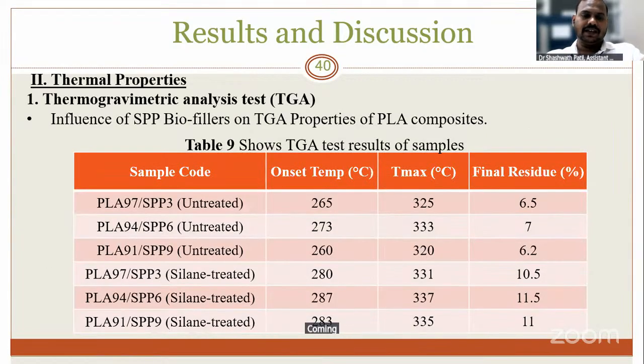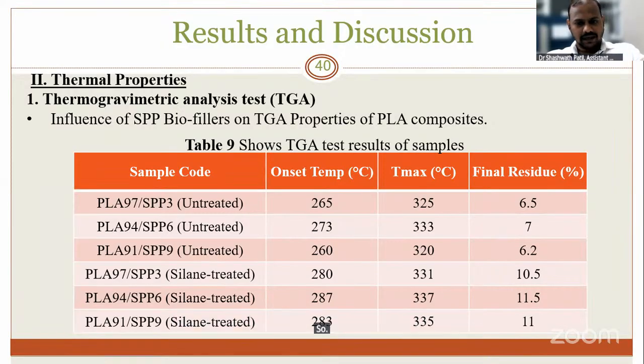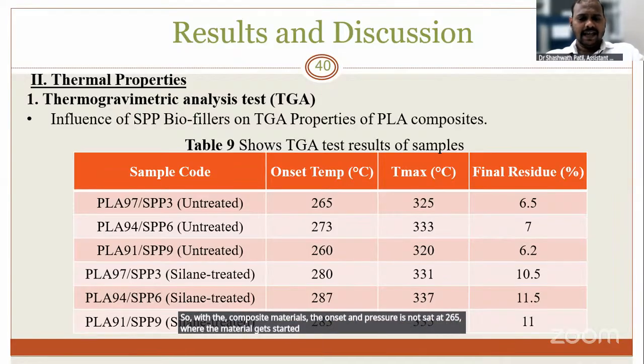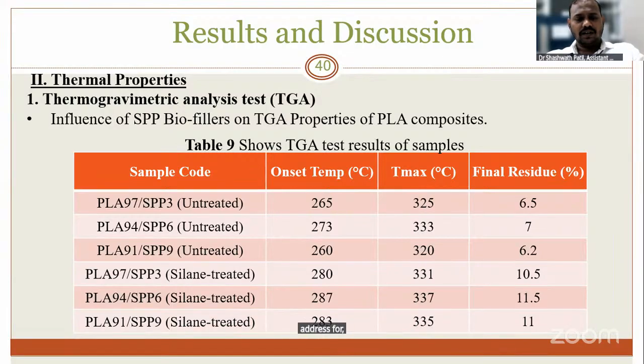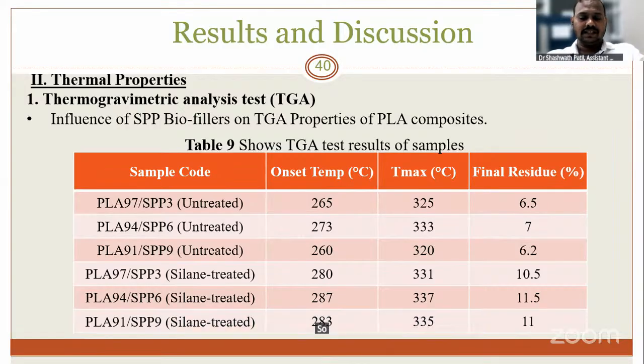Coming to the thermal properties, the influence of the reinforcement material on the PLA: usually PLA has a melting temperature in the range of 150 to 160. With the composite material, the onset temperature started at 265, where the material starts degrading, and it reached up to 283 degrees. For the 6% silane filler, we have achieved a maximum of 337, with the final residue, that is ash or powder after burning, of 11.5%.